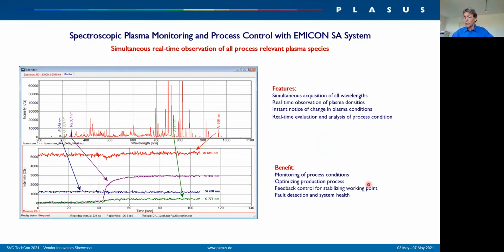How we do this is shown here. You have the spectrum in the upper diagram, and you see the different lines. You have, for example, the argon line in red and the silicon line in blue, but you can also monitor the oxygen line or the nitrogen line for the gases you put in. On the lower diagram, you see the monitor tracks, and this is what you make use of in your process. Everything is stable until you open the valve for the gas flow. Here it was an air gas flow, and the nitrogen line and the oxygen line come up and show you the difference.